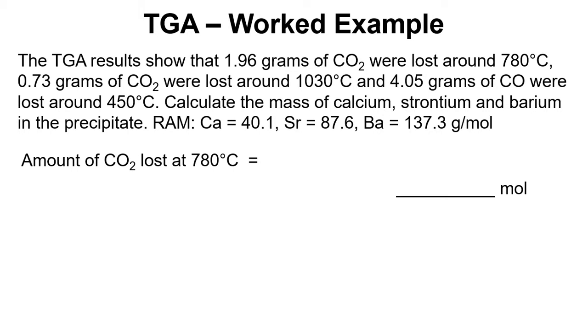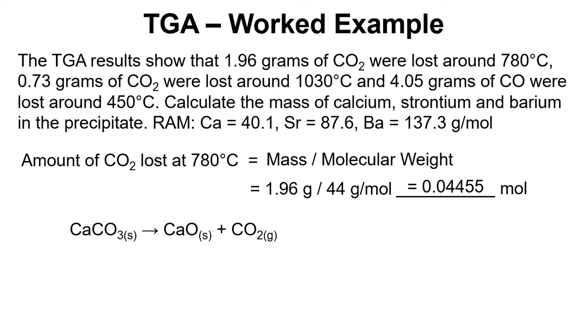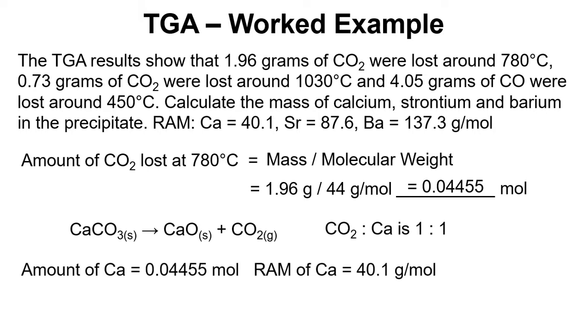So the amount of CO2 lost at 780 is mass over molecular weight, we've got 1.96 grams and the molecular weight of CO2 is 44 grams per mole so we have 0.04455 moles of that material. Now based on the decomposition equation the CO2 to calcium is one to one. So the amount of calcium is also 0.04455 moles.